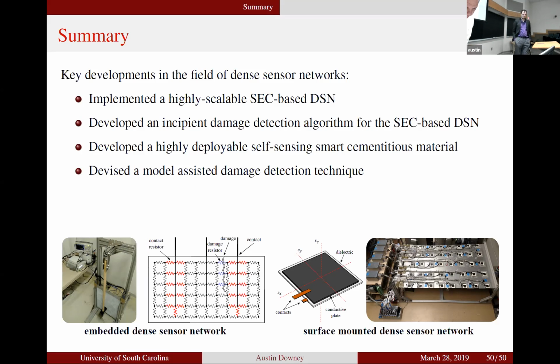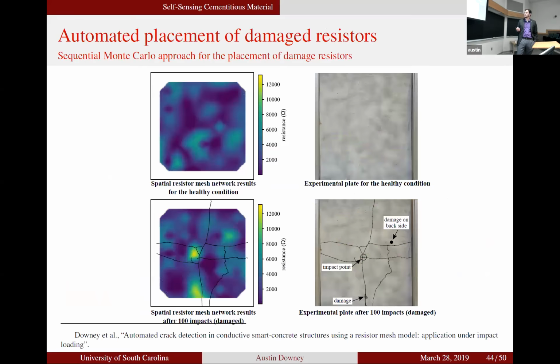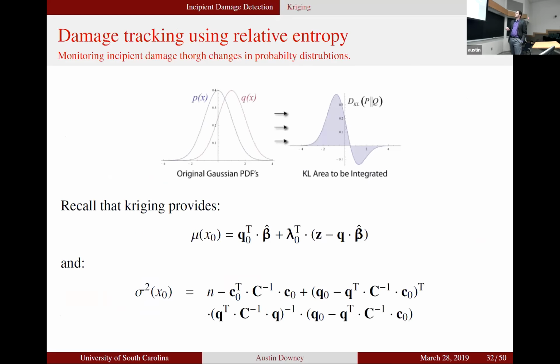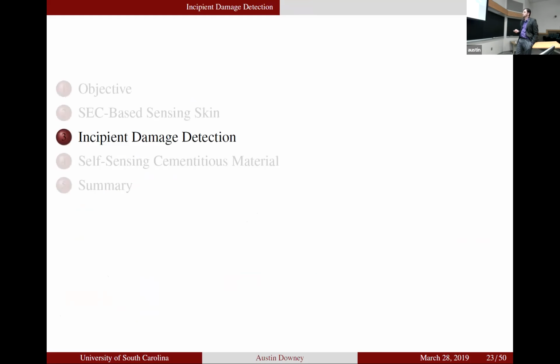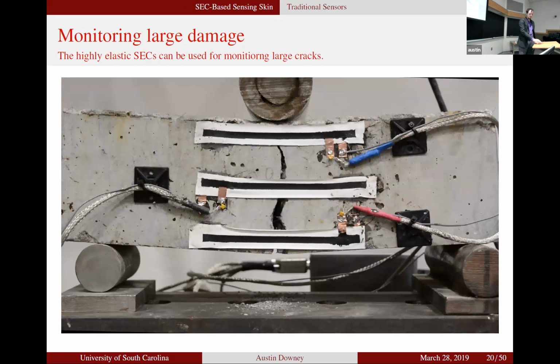If you want to type in your question, okay: why don't you glue the sensors fully on the concrete when you monitor the cracks? What is the minimum crack size that can be detected? Yes, let's go back to that because that's actually an interesting question. If we glue the sensors directly, completely under, right? So right now it's glued on the edges. If we glue it completely under, we're actually not monitoring the expansion of that joint. We're monitoring cracks in the glue.